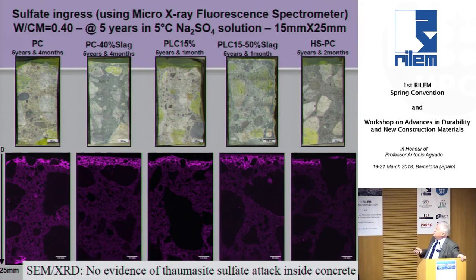And whether it had limestone or this straight Portland cement with or without slag, there's a 15% limestone with or without slag, and then a sulfate-resistant Portland cement. It didn't have much impact on the rate of penetration, and we never saw any Thaumasite inside the sample. The only time we saw Thaumasite was when pieces fell off the surface, and they then further deteriorated in the structure.